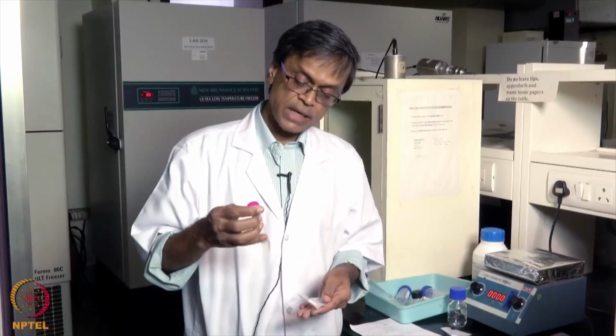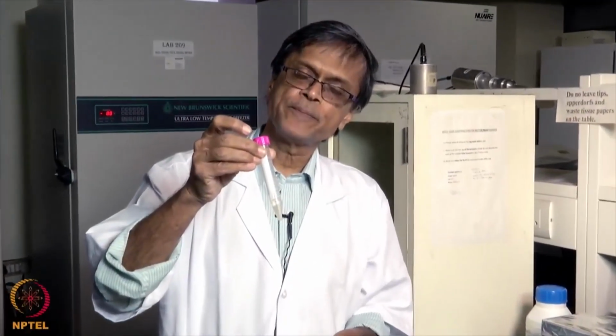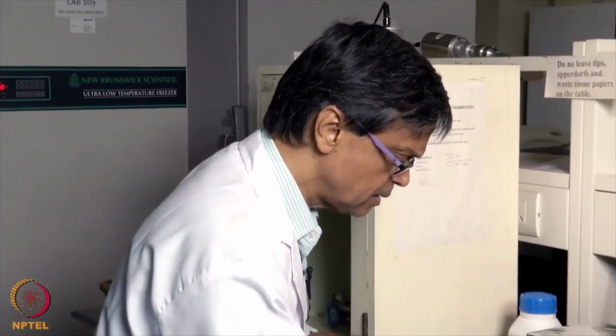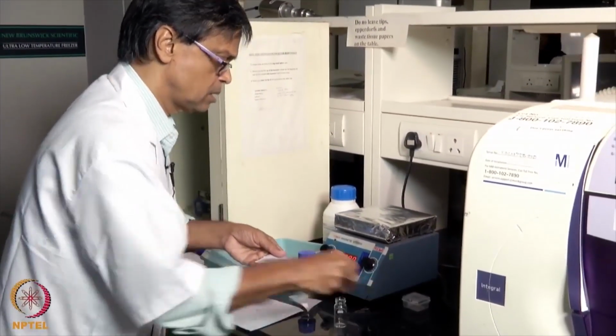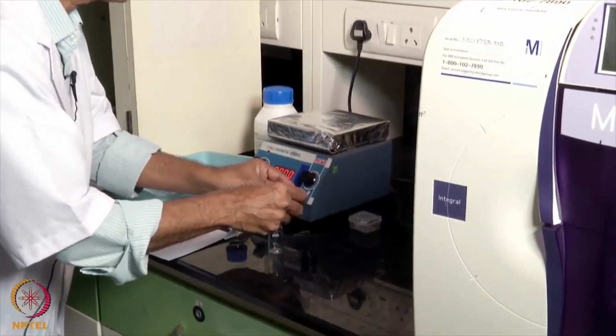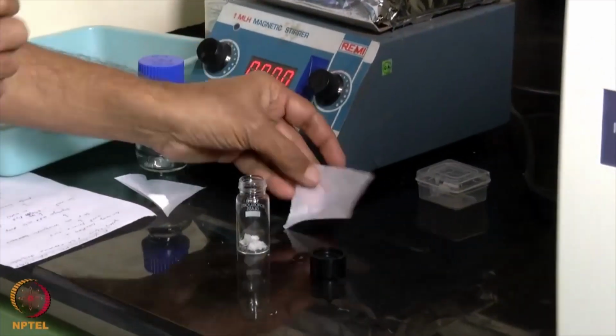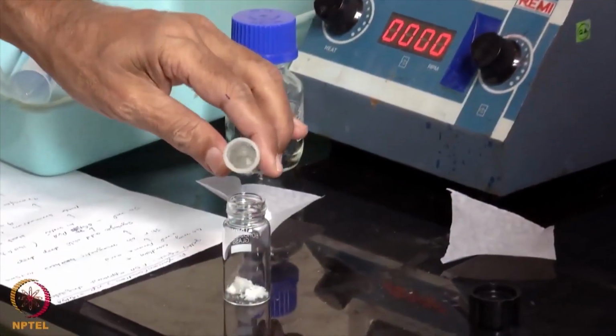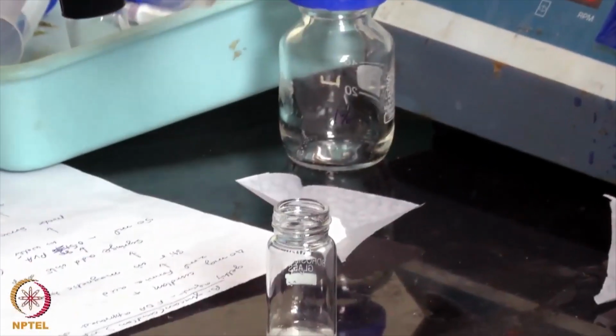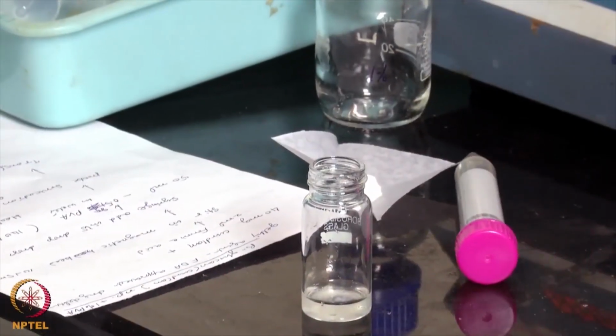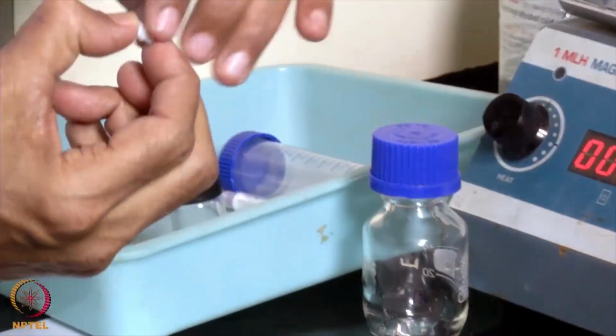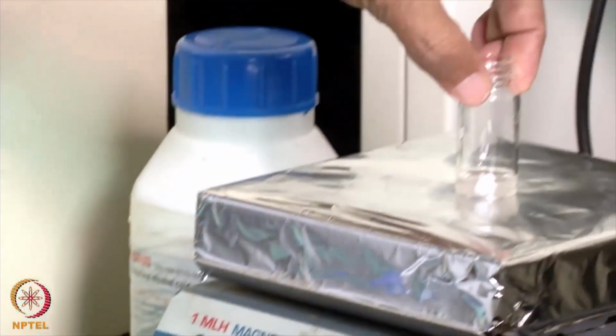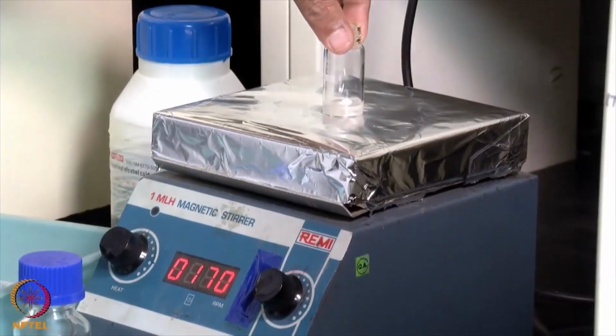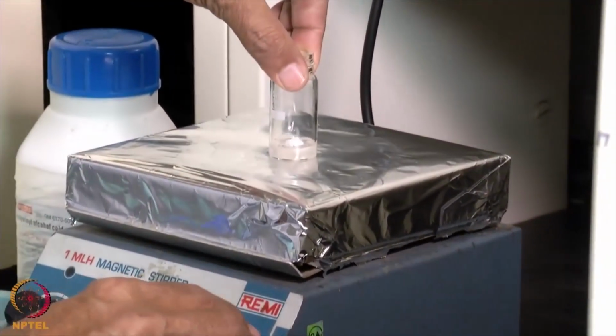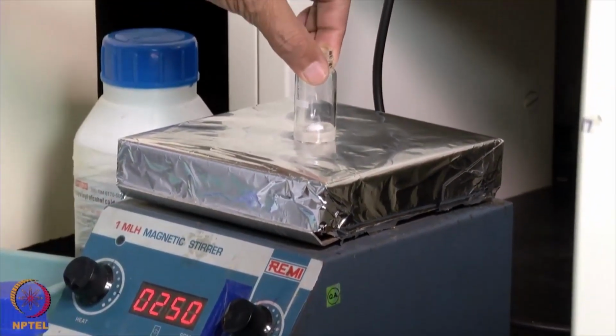So I have taken 40 milligrams of Curdlan or beta glucan. I have taken 2 ml of formic acid, and we are going to mix them at room temperature using a magnetic stirrer. As you can see, this is the magnetic stirrer. I put it inside, and then I stir it. So we stir it for about 5 to 10 minutes so that it completely dissolves into it.